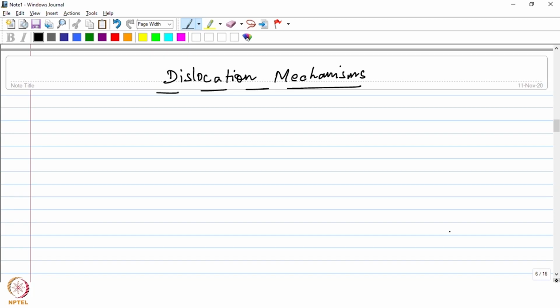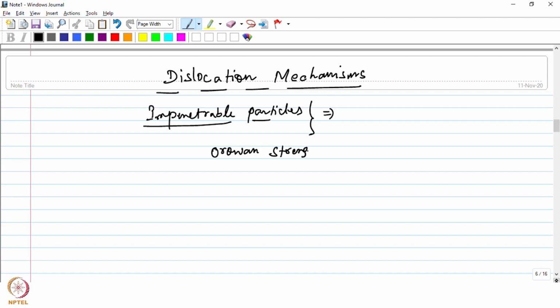So when you have this kind of solid impenetrable particles as the reinforcement, then obviously this is going to act as the hindrance to the motion of dislocations, and we can in fact invoke the Orowan strengthening mechanism here. The Orowan mechanism talks about the bending of dislocations around this kind of impenetrable solid particles when they are dispersed in a matrix phase.